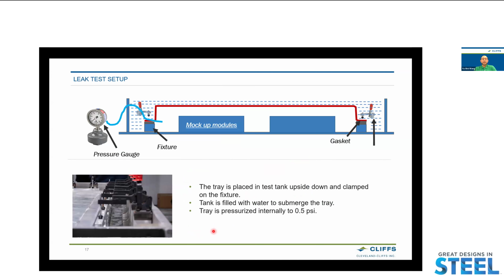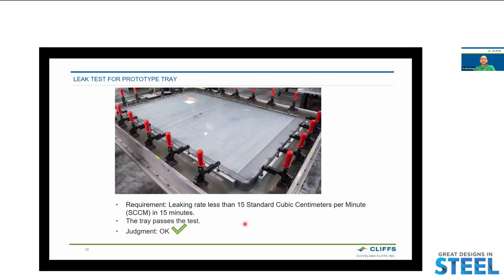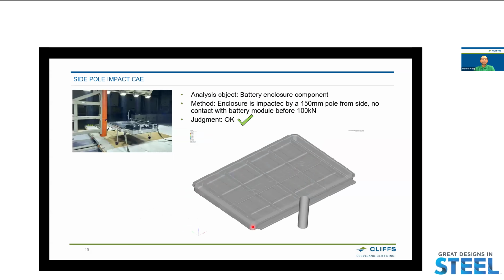And this one shows the configuration setup of the leak test. The tray is placed in the test tank upside down and clamped on the fixture. The tank is then filled with water to submerge the tray, and the tray is pressurized internally to 0.5 psi. Besides the flange flatness, the laser weld line was also a point of concern that may be a potential source for leak. As you can see from this test, both the flange flatness as well as the laser weld line passed the test, meeting the requirement of leak rate less than 15 standard cubic centimeter per minute. And we passed the test with flying colors.